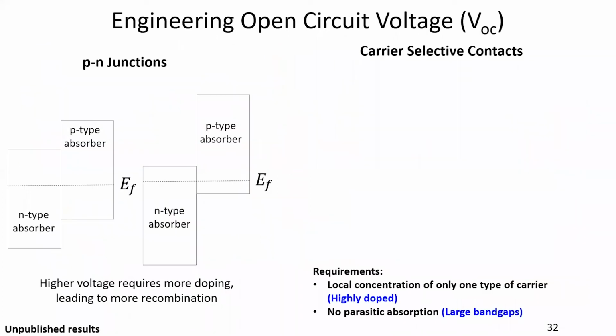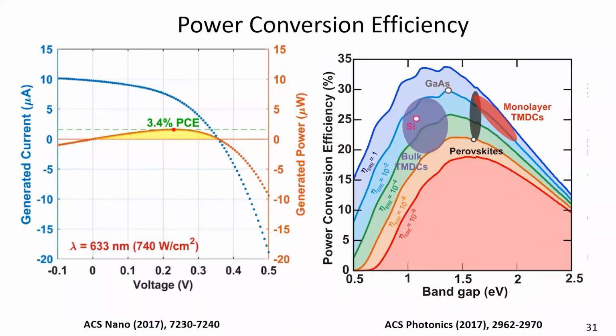The real place it is being stuck at is actually the open circuit voltage. In terms of absorption, we already have a lot of absorption. Carrier collection should not be bad. As I told you, internal quantum efficiency is approaching 70%. Then you should be limited by voltage. And of course, we are being limited by voltage. In fact, if you look at our open circuit voltage, it is very low. It's about 0.35 V, and if you look at the band gaps, it's about 1.2 to 1.3 eV.